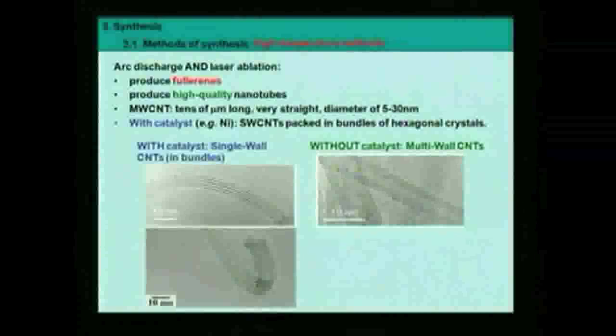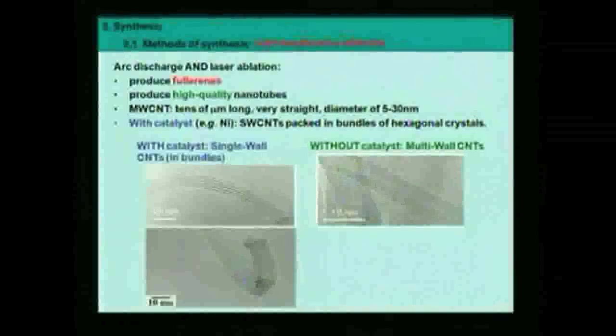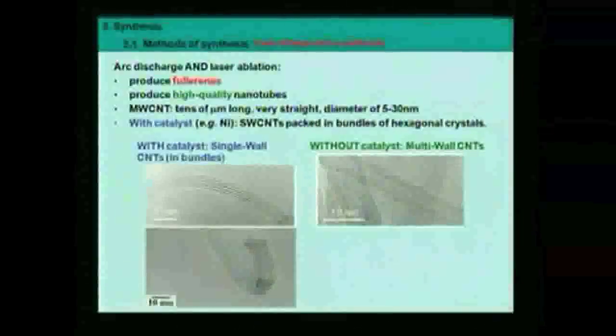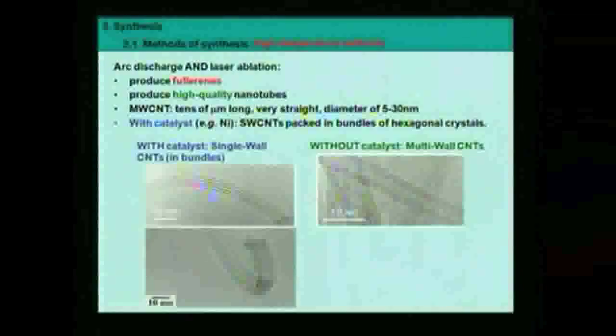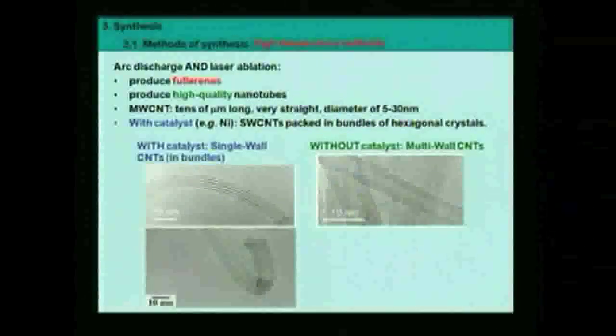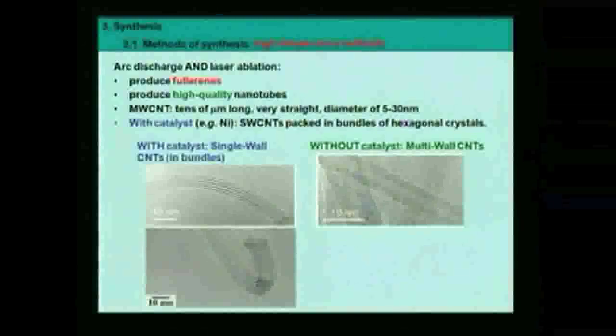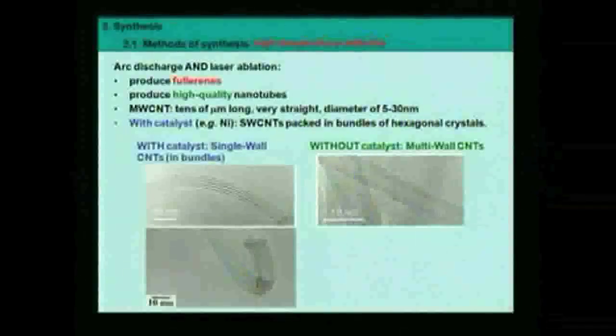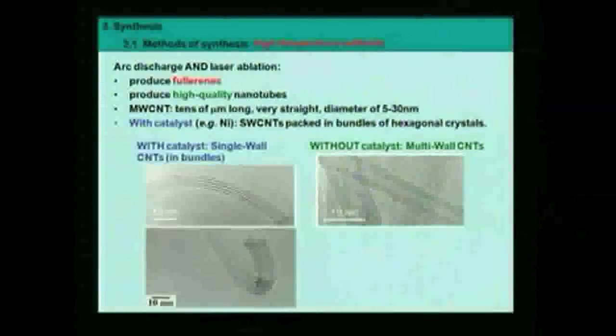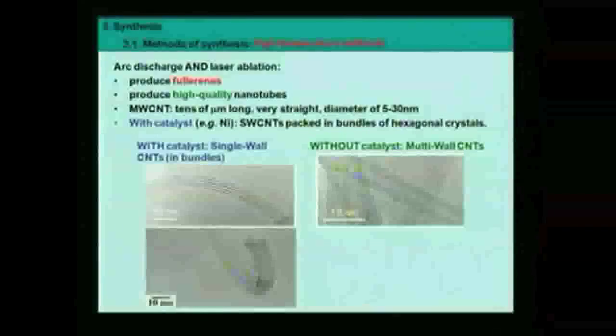We will see that when using medium temperature techniques, a real problem is to make structures without too many defects. It's more difficult. It's possible, but it's more difficult. Here, it's intrinsic. You do not have to do anything special. They are always high quality. The length can be tens of microns long. The multi-wall nanotubes, as you can see here, are very straight. Their outer diameter is between 5 and 30 nanometers.